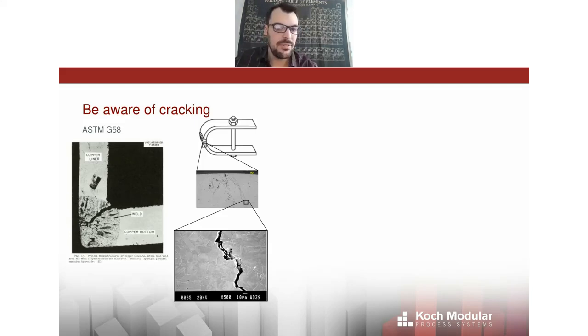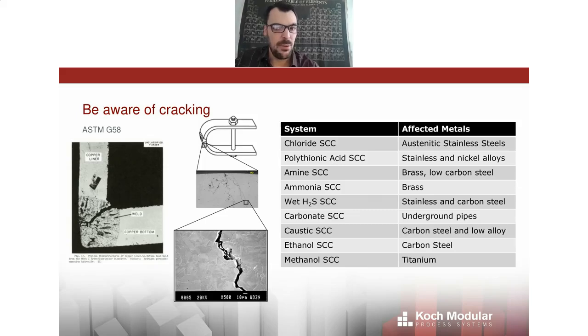Probably everyone's heard of chloride cracking for stainless steel. All austenitic steels are susceptible to chloride cracking, but there are about 10 or 12 known cracking mechanisms. So amines and ammonia are known to crack brass. Caustic and ethanol at high enough temperatures can crack carbon steel. Methanol can crack titanium. There are a marvelous and wide range of cracking mechanisms, and you don't want to use a metal that's very robust in terms of mils per year. Wall loss is negligible, but it has a cracking susceptibility.